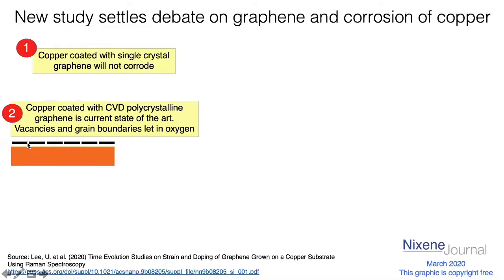Polycrystalline graphene has these little gaps and cracks in it. And that's what's actually on the surface. So you remember both those copper samples I showed you before, you can't see it with the naked eye, but down at the microscopic level, this is what the surface looks like. It's not as regular as this. It's a bit like crazy paving. There's holes and gaps. And the thing is, these grain boundaries let in oxygen. So this black dotted layer here represents the polycrystalline graphene, and the orange block here represents the copper foil.